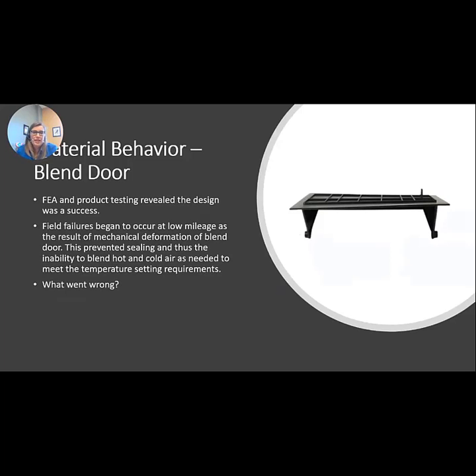So FEA and product testing looked good. So they went to market with this design and they started to see field failures again at low mileage. And what they were starting to see was deformation of the blend door you see here. On the bottom of the part, you have two areas where you essentially are pivoting the door. And then this tab here is where you would actuate the door during adjustment of your temperature controls.